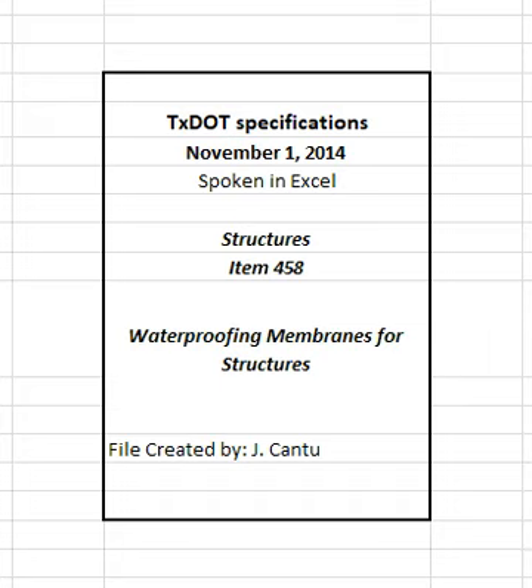Ensure surfaces are free of contaminants such as form release agents, wax base curing compounds, oil, and grease. Remove any contaminants by abrasive blast cleaning. Ensure there are no depressions or pockets in horizontal surfaces of finished waterproofing. Fill expansion joints and other grooves with plastic cement conforming to the requirements of DMS 6300, waterproofing, unless otherwise required on the plans. Ensure joints are dry and clean when filled. Overfill slightly to allow for shrinkage in drying.